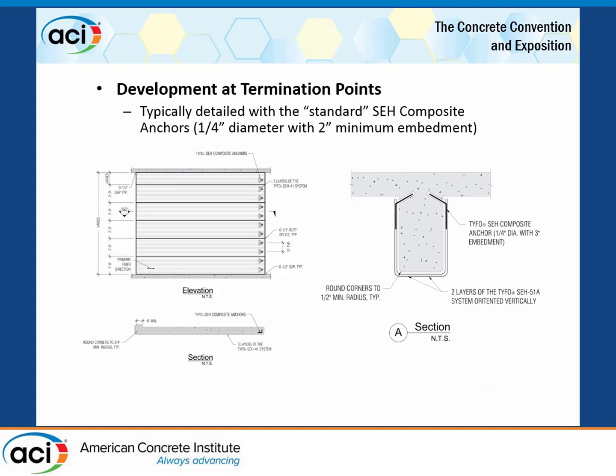You can improve the performance of walls. We did quite a bit more wall testing with and without anchors. The detail you see there with the beam is more or less what we tested at UT Austin. By the way, whether you go straight in or whether you angle, six of one, half a dozen of the other, but in terms of where you drill the hole, you can't drill the hole all the way up against the soffit if you go straight in because of the dimensions of a drill. You're going to end up 1.5 inches or 2 inches below the soffit because of the drill. But if you slightly angle that, you can get the hole right up at the top, closer to the compression zone. I'm trying to get my tension member up into the compression zone.